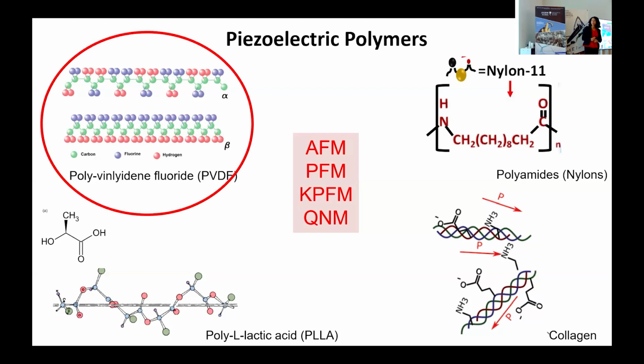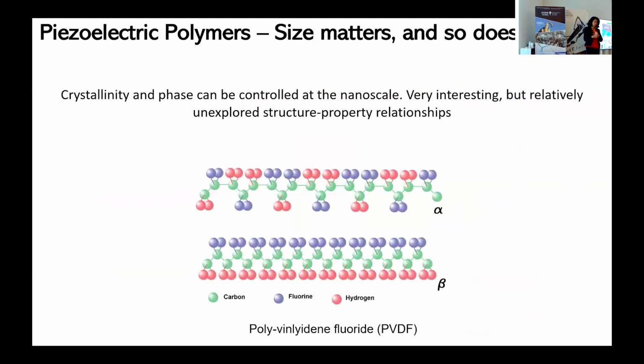So let's start with PVDF, or polyvinylidene fluoride, which is kind of a poster child for piezoelectric polymers. So as I mentioned, size matters, because when you go to smaller scales, you can control better the crystalline properties, and you can also control better the alignment of these chains. But so does phase. So phase is very, very important. And let me explain what I mean. So here's PVDF, the structure of PVDF. So you have a carbon backbone, and you've got hydrogen and fluorine atoms on either side. It usually crystallizes in the alpha phase, which is the thermodynamically stable phase. And you can see that the hydrogen and fluorine atoms are randomly distributed across the chain.